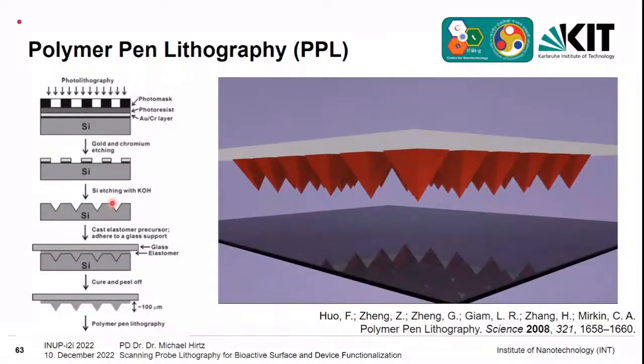This only needs to be done once, and then you have the master here. This master can always be replicated with an elastomer, most of the time PDMS with a glass support. You take it out, cure it, peel off, and you have your pen or your stamp for the polymer pen lithography. And then you can use the master again. You can always start again from this step, fill it with elastomer, put a glass slide on it, and take off the next. You can do this for hundreds, if not thousands of stamps. So it's also an inexpensive way of producing your probes.